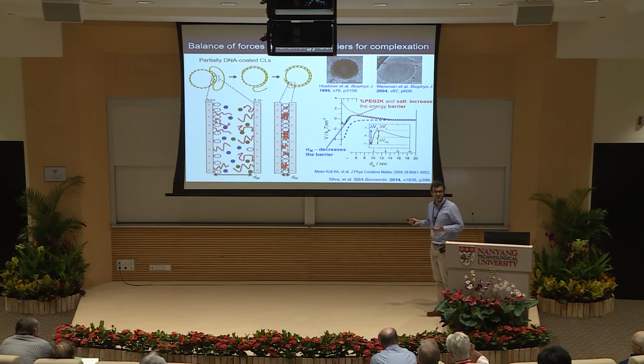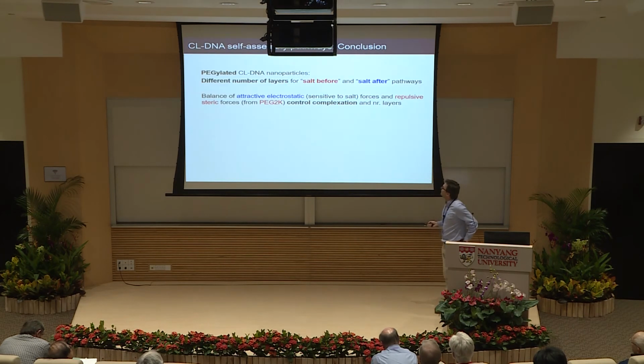And if we have salt at the moment that we are making the complexation, we decrease our attraction, so we get this bump here. But this is just a barrier, because the compacted state is always the lowest energy. So if we have our particles formed already and we add salt, we don't seem to affect them that much. So, to conclude,